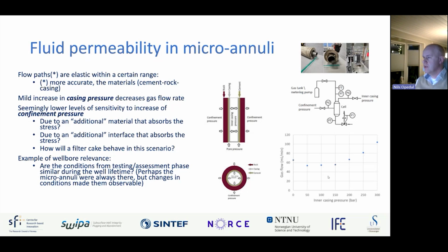So how to do this? There's a very basic P&ID of the permeability test setup where we have a cell. So we have multiple cells, which we are able to manipulate the confinement pressure, the inner casing pressure, and also the pore pressure. So we can do a magnitude of different things to our cells here. What we see when we do this kind of test is that the flow paths, or the microannulus, are elastic within a certain range. And when you say flow paths are elastic, it means in essence the materials, cement, rock, are elastic. That means that, for instance, if you have a mild increase in casing pressure, you can observe a decrease in the flow rate. That is also reproducible when you deplete the pressure.